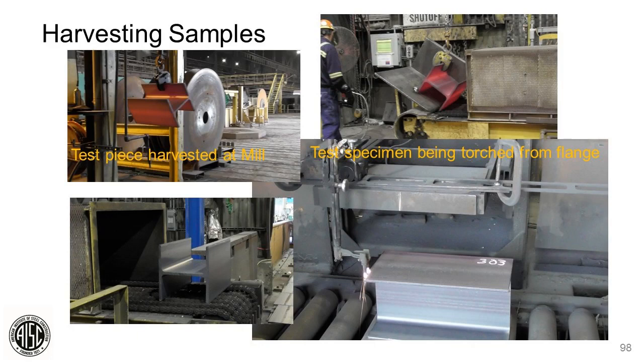And this is an example of a piece being harvested off the mill, a piece being moved on the top right. Again, more equipment to move it. Now, I should have jumped right to this lower right picture, where we have the torches cutting out the coupon. Again, ASTM specifies the web center to the flange tip, 1/3 of the distance, is where the longitudinal center of that specimen is to be, and that track torch is set a uniform 2 inches apart, so it always cuts a 2-inch coupon out of that flange. Next slide.